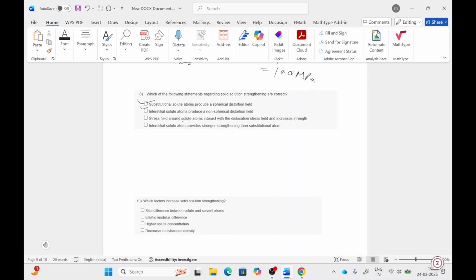Next, the stress field around the solute atom interacts with the dislocation stress field and increases strength, so the third option is also correct—meaning the interaction between the stress field around the dislocation and the solute atom results in strengthening. The fourth option says interstitial solute atoms provide stronger strengthening than substitutional atoms, which is also correct, since interstitial strengthening is higher than substitutional.